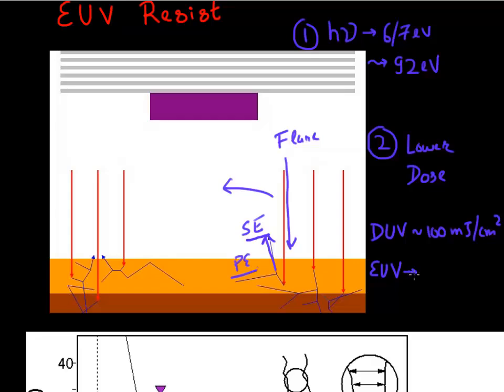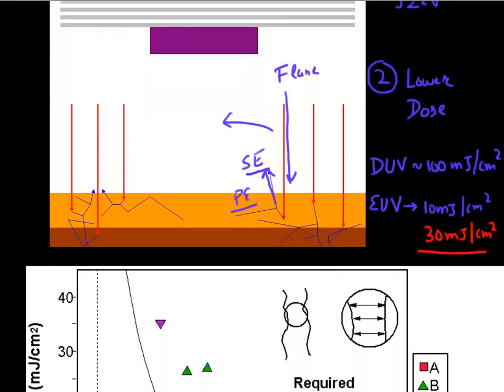People want EUV resist to operate at a dose of 10 millijoules per centimeter square, which is the target. More realistic resist operates around 30 millijoules per centimeter square. The problem when you operate at such a low dose is your line edge roughness.